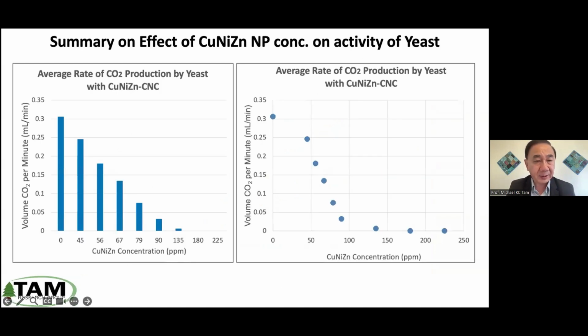And then we can plot this CO2 release versus the concentration, and from there you can determine that for this particular system, about 100 ppm would be sufficient to prevent the yeast from producing CO2. That could mean that the yeast had died, or the yeast metabolic activity is being substantially reduced.